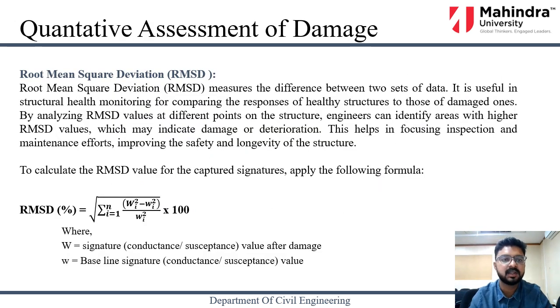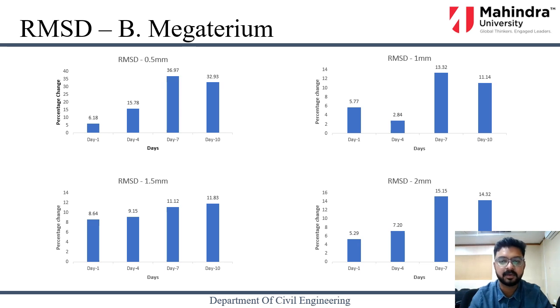So that's why we have also done quantitative assessment, which is using root mean square deviation, also called RMSD. Generally this RMSD will give us the percentage of change between the baseline data and the data which you have acquired. Here we can see for the 0.5, 1, 1.5 mm and 2 mm cracks, the RMSD is changing, which says that there is some change. But as I said, though this is a quantitative analysis, we haven't got the exact amount of healing. There you can see at day 7, there is a maximum shift in all the RMSD values. And then we thought this might be the case where healing is happening.